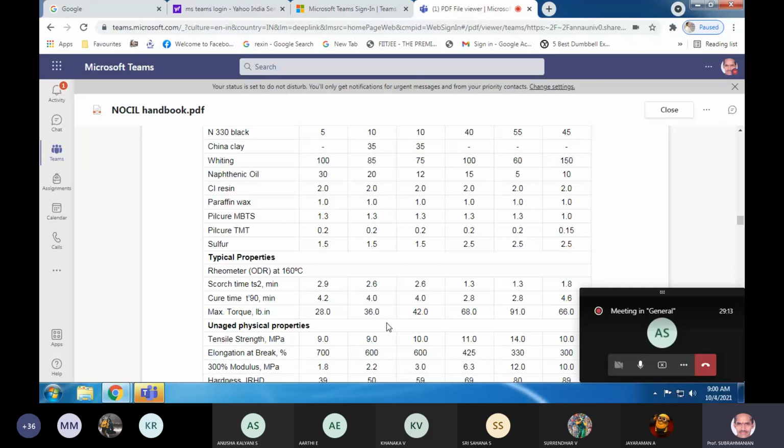So, scorchy meaning you may not be able to drop the compound in the proper fashion when you prepare the mix the first time. All right. This scorchiness is definitely an issue when you do repeated warming. At a later stage, you consume some quantity and preserve the remaining compound, maybe to be used after a month or 2 months or so. At that time, the compound should be plastic enough. Okay, it has to be elastoplastic.